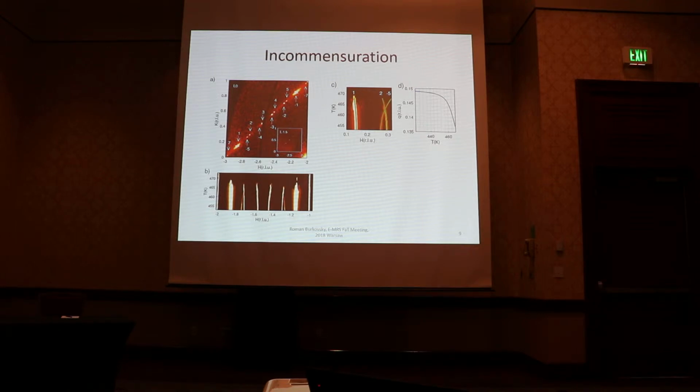This is our experiment. We put very, very strong synchrotron light on this crystal to have many, many, many orders of the reflections, big orders from 7 to -7. So this is the parent reflection, first, second, third, and finally, when you jump over the Brillouin zone, you arrive here, this is the 7. So the whole Brillouin zone is jumped over by this incommensuration. What is good is that you can be very sensitive to the changes in the modulation wave vector. This is what's happening with temperature on this structure. It starts from a particular place where these two reflections overlap, and then they evolve with temperature quite smoothly. In the large picture, you see this intersection of the second order and -5 order. It allows us to reconstruct very precisely the modulation wave vector.